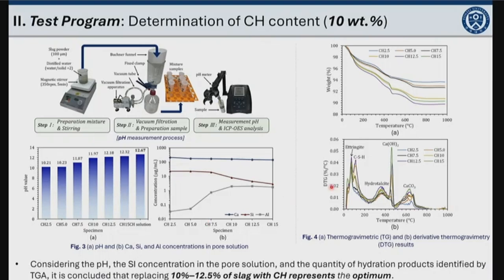Based on the derivative gravimetric result, 10% and 12.5% of calcium hydroxide produce the highest amount of CSH gels. So even though it is difficult to conclude that 10% calcium hydroxide is the absolute optimum dosage, this level is close to the optimum in terms of the hydration reactions. Therefore, 10% calcium hydroxide was adopted in this study.